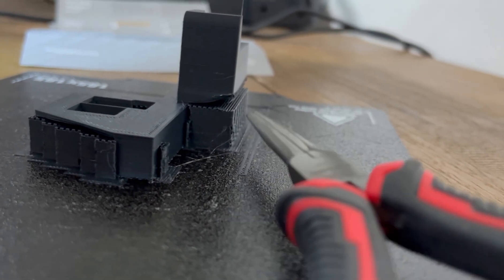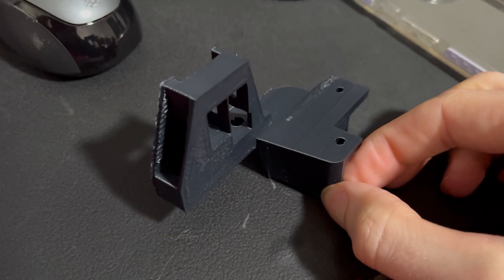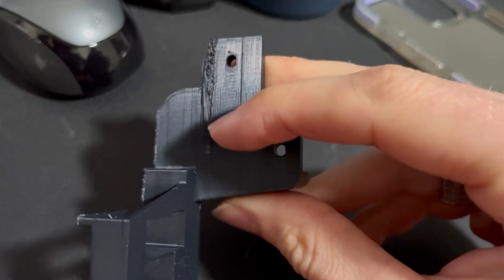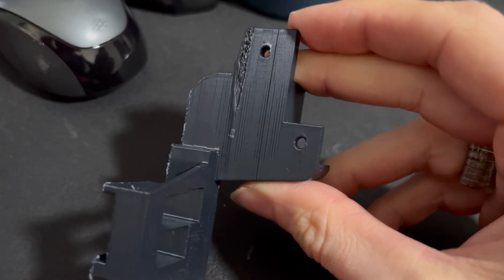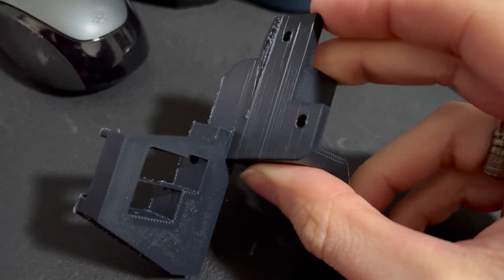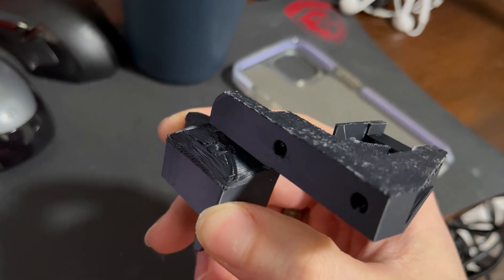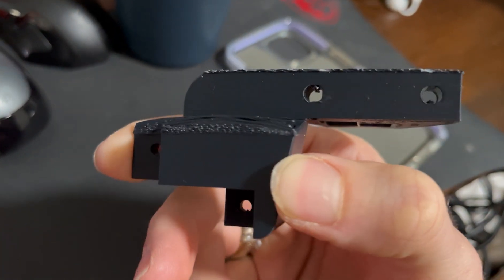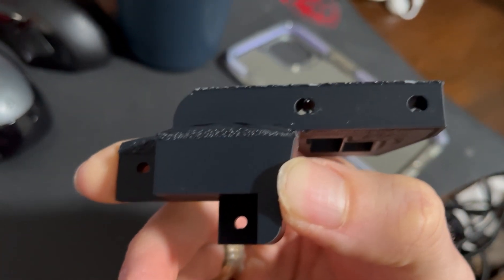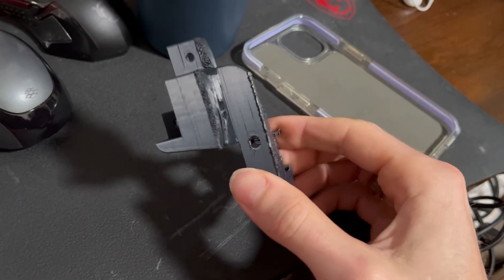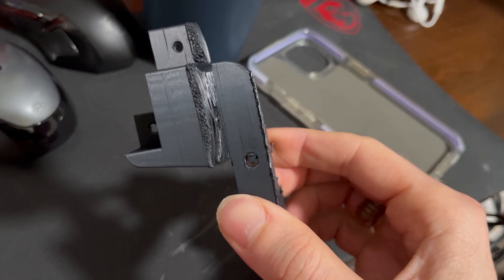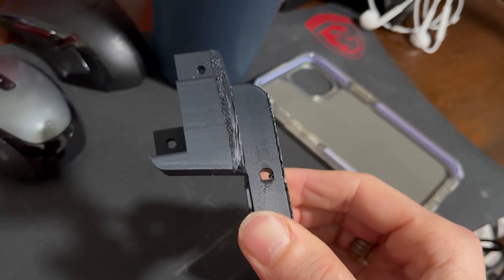So you know how we had to use magic goo to get the ASA filament to stick to the bed? Well the supports stuck to the bed, and then when it got time to lay the layer of ASA filament on top of the supports, the ASA did not adhere to the support layer. It warped, causing the layer to curl up from the support.